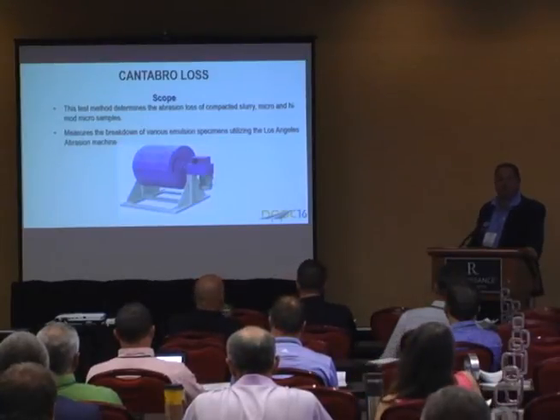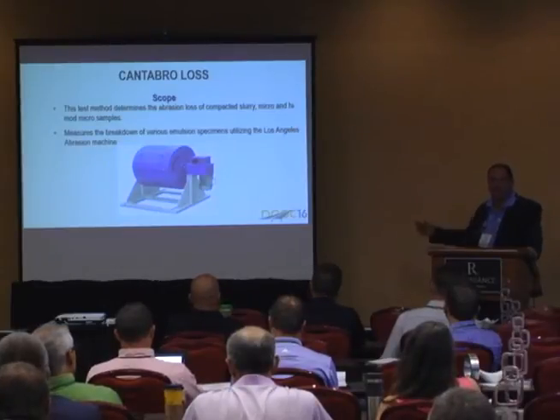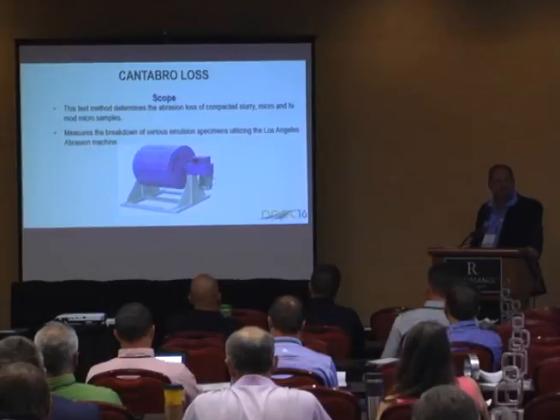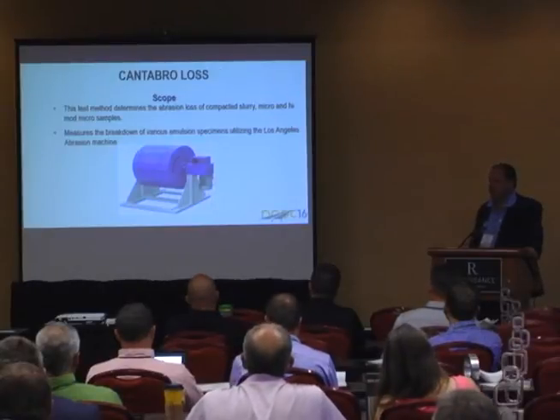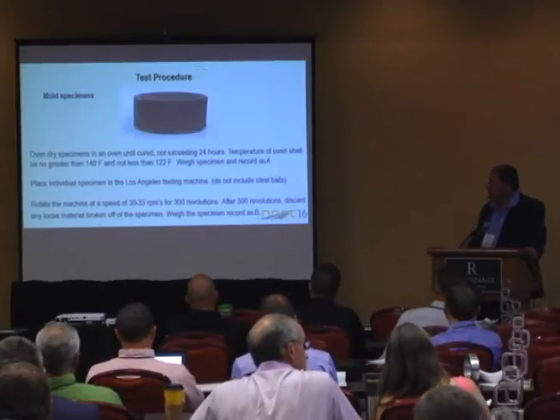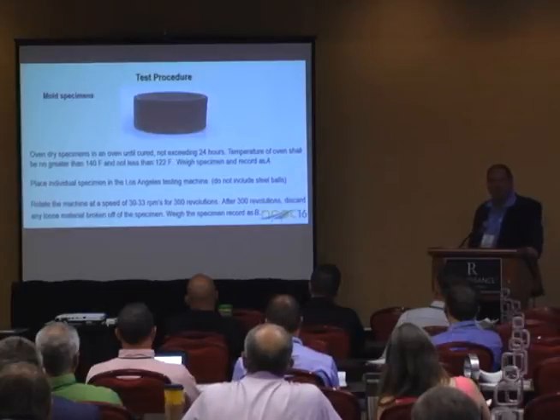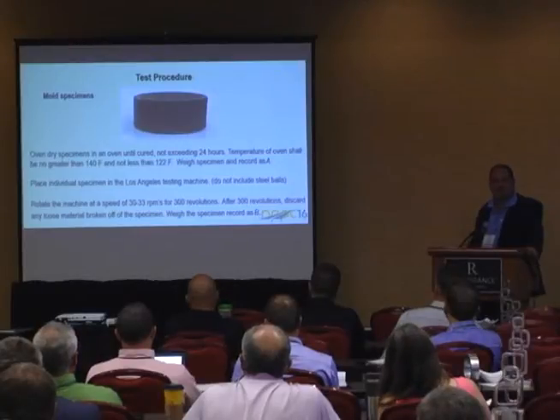It has a paddle. If you've never seen this, it's just a drum with a paddle. No charge medium at all. We're going to let this run 300 times for the Cantabro, or Cantaburo, depending how good your Spanish is. That's who developed the methodology. We're going to put our sample that we've compacted with a gyratory compactor into the Cantabro. We're going to let it run 300 revolutions, and we're going to measure the loss.